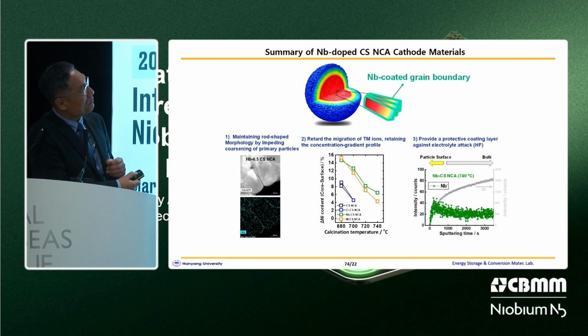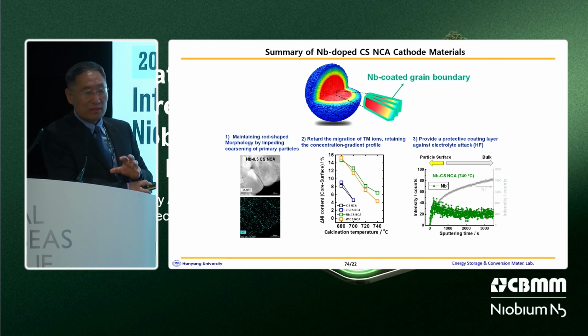Niobium doping contributed, first, to maintaining the rod-shaped morphologies by impeding coarsening of primary particles. The second is retarding the migration of transition metals, retaining the concentration gradient profile. And the third is providing protection of the coating layer against electrolyte attack, especially HF.